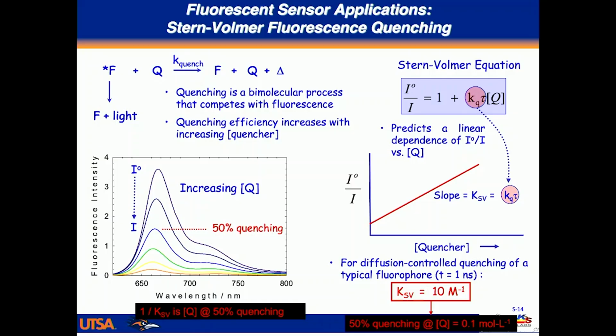Okay, so in other words, it's how much I need to add to drop this intensity down to half of what it started at. So now if we think about a sensor, a 50% reduction in intensity would be a pretty good response. So that would be a reasonable fluorescence response to the presence of an analyte. But if you're an analytical chemist, you're going to conclude that this is a pretty poor sensor because you're going to have to add 0.1 mole per liter to get a 50% signal. Okay, so this is a bad sensor, but it gives you the idea.